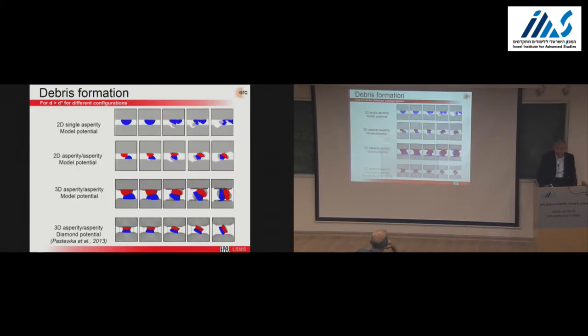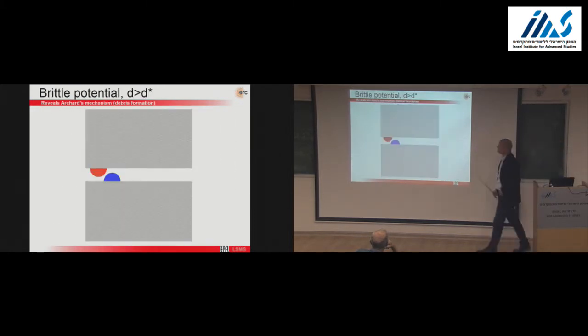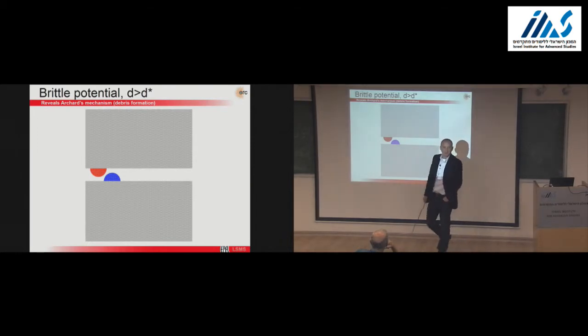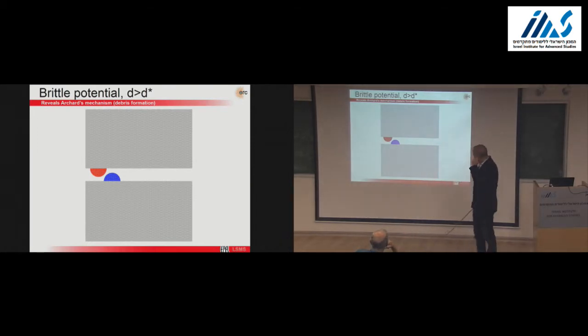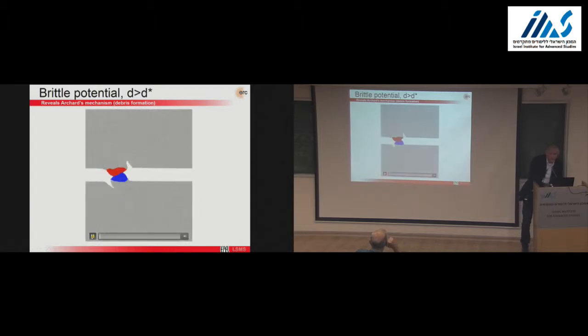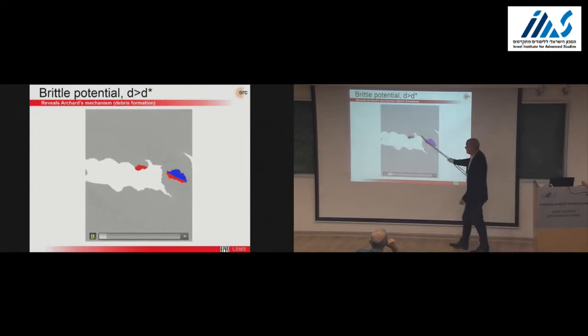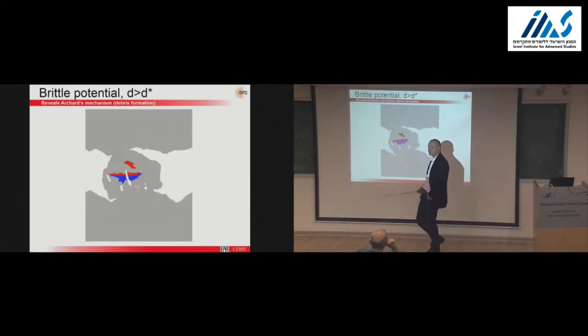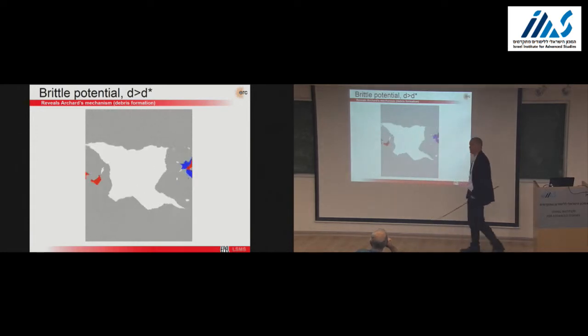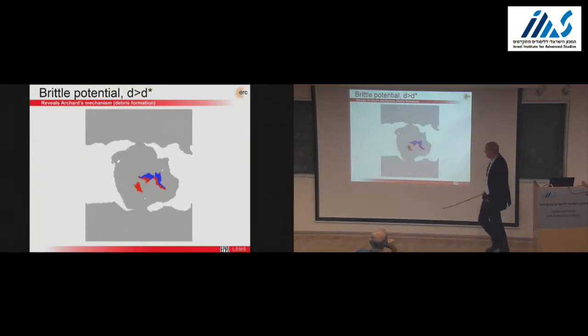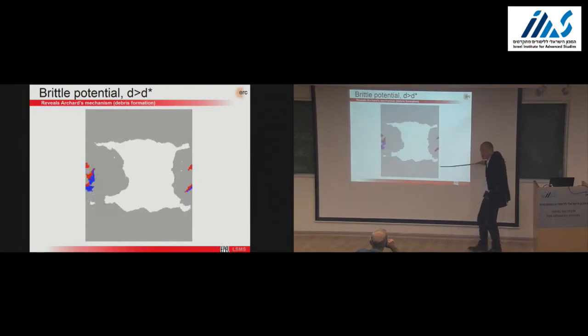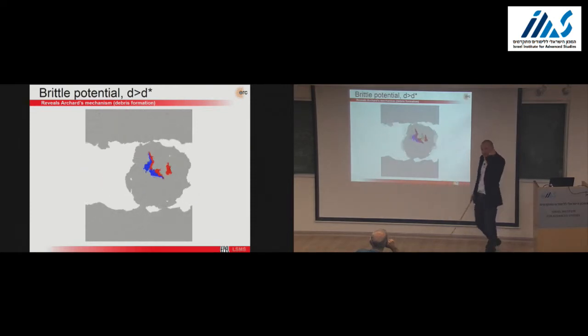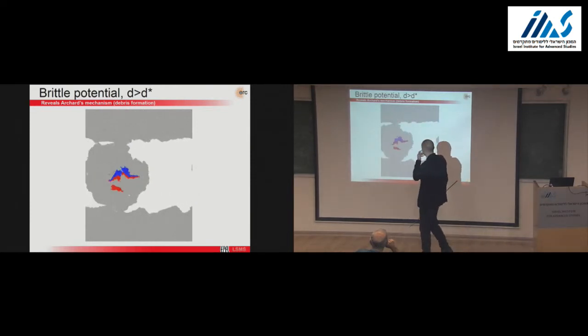But if we pick D larger than D star, then a miracle happens where we see something very different, and we get Archard debris formation mechanism, and we got really, really excited about this. You form cracks, you form a debris that starts to roll, like what Zev may be seeing in rocks. You start to develop roughness naturally, although the surfaces were flat. And I think we have a lot of information to dig from there.